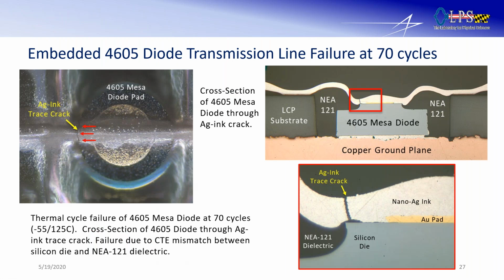All right, and again, it's not to say we didn't have some initial problems, and this was one of them. The first generation that we printed, that I showed the picture of, we thermal cycled that. We actually had an early failure at 70 cycles. This is a metallographic cross section, and it shows a crack in the silver line right on the edge of this MESA diode chip.